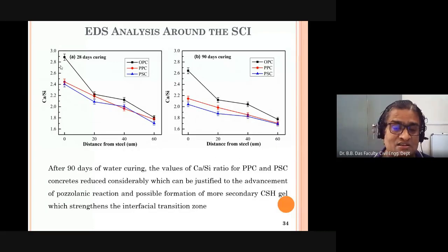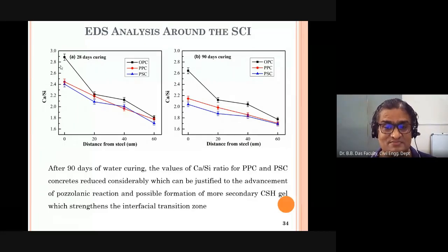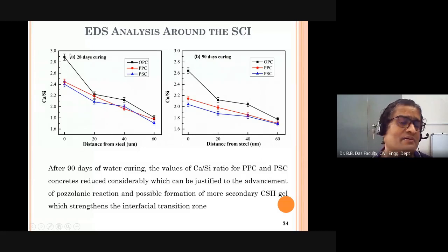The cement grains close to the steel surface are not converted into calcium silicate hydrates. Remember this. But the moment we come down, I get a Ca by Si ratio of lower magnitude. Near the ITZ, near the steel surface, there is more formation of calcium hydroxide as compared to calcium silicate hydrate. The same is shown for 28 days and for 90 days. Our topic is to compare OPC, PPC, and PSC.